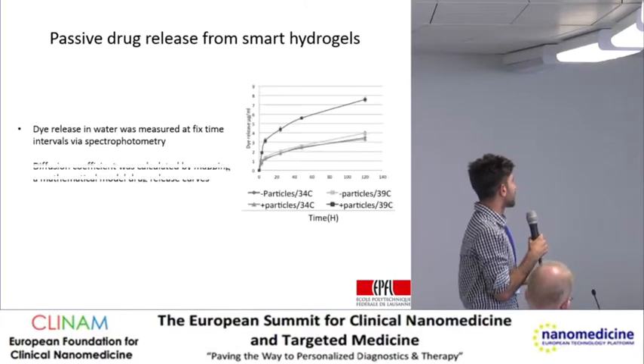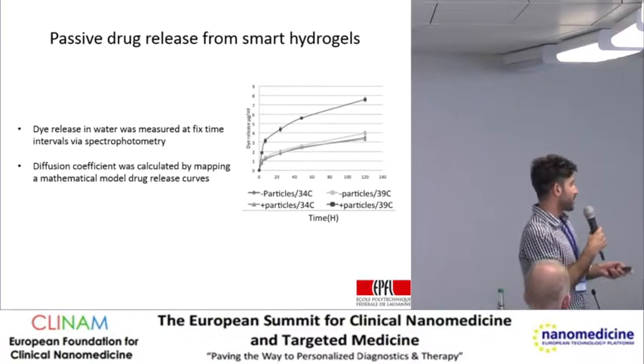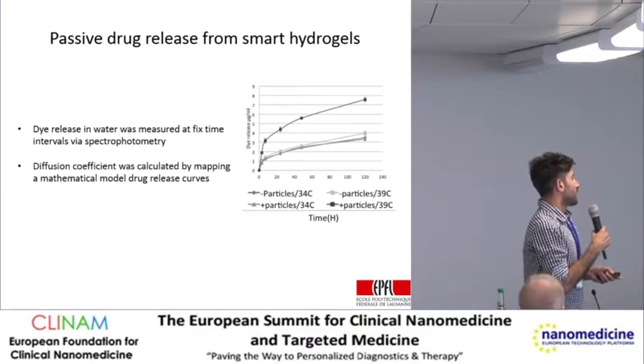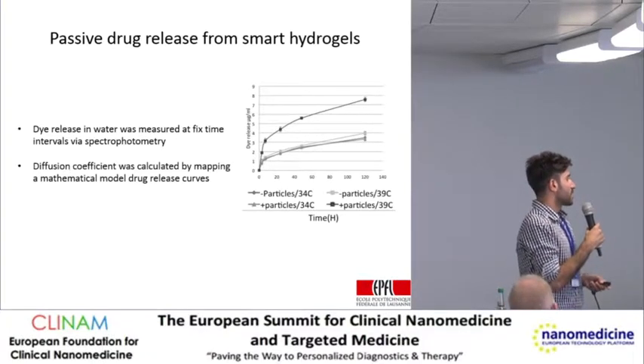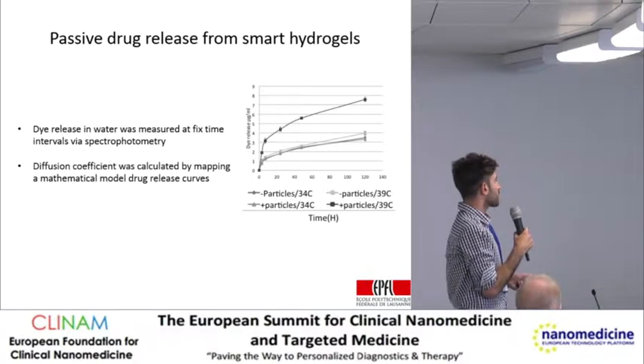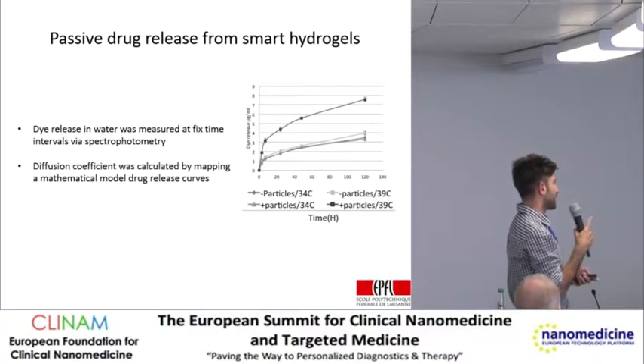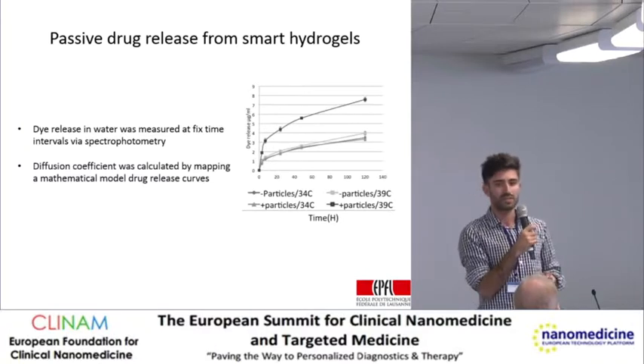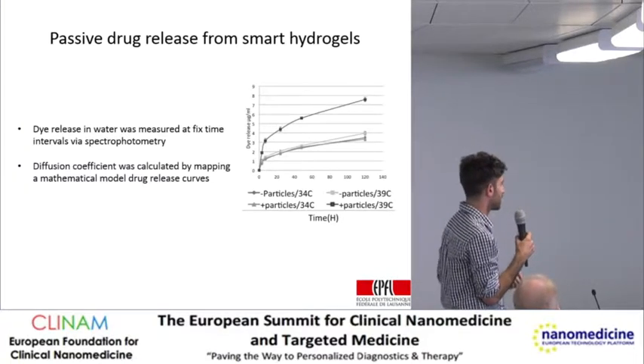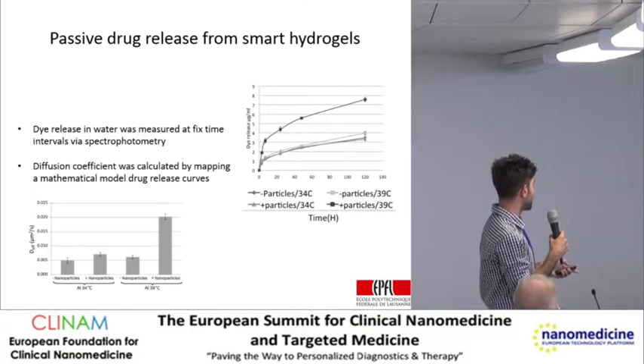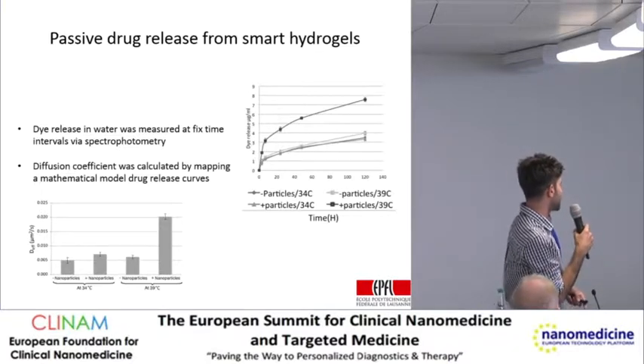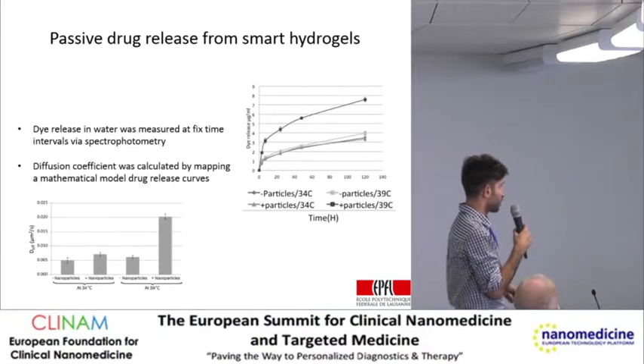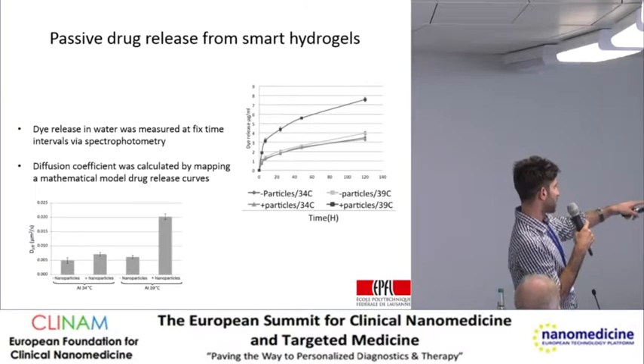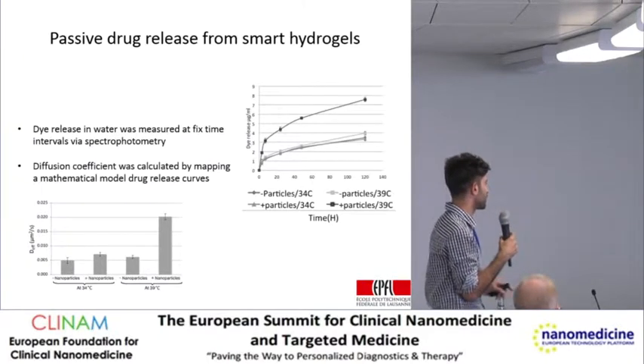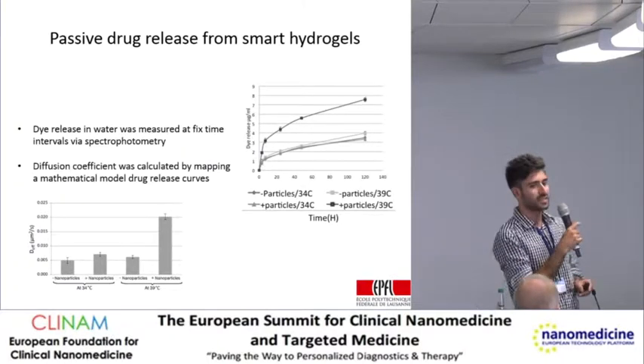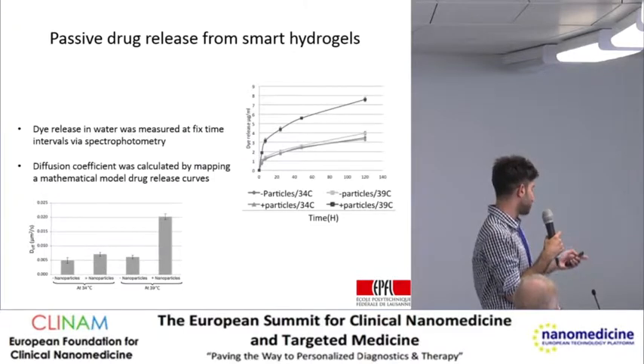And then we found that the group with nanoparticles, which were incubated at 39, had much more release compared to the others, which means that the thermosensitivity of the nanoparticle works even without mechanical load. And the diffusion coefficient that we measured experimentally for this hydrogel showed that the hydrogel is about three times more permeable at 39 degrees compared to 34.